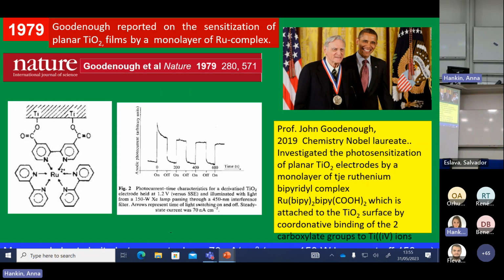But you can see that at the end, the current coming out is in the nanoamp range. Just compare this to 40 milliamps for silicon photovoltaic cells. They're 6 orders of magnitude off what you need, a factor of 1,000,000. And so when I was a young postdoc, people said I shouldn't touch the area. It's hopeless. And for that very reason I just explained.